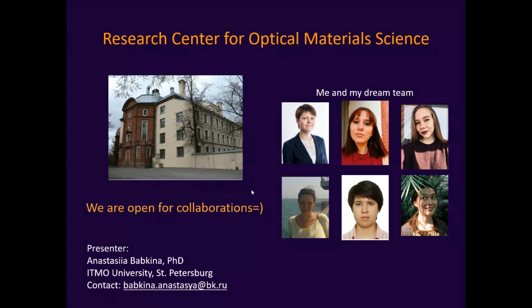XRD can't properly help us obtain this size. TEM also, by this moment, couldn't help us. The only thing that we can do is to take spectroscopic results, namely the absorption spectra at low temperatures, and use the mathematical theory designed by Efros in 1982 concerning the size of a semiconductor quantum ball. We use this model, and we calculated that indeed our nanocrystals can be synthesized in sizes from 2 nanometers up to 7 nanometers.